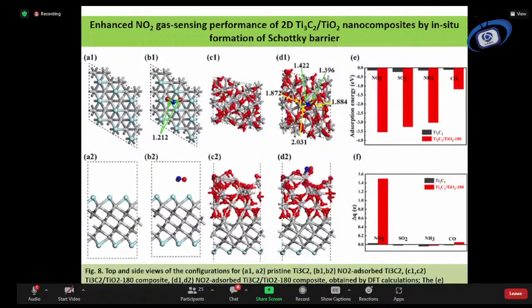You can see both in figure E and F. They show a maximum response even for the simulated one, and also, of course, the experimental one, because that has been experimentally proved, and it gives a very good adsorption energy, and also ultimately high response for nitrogen dioxide gas.